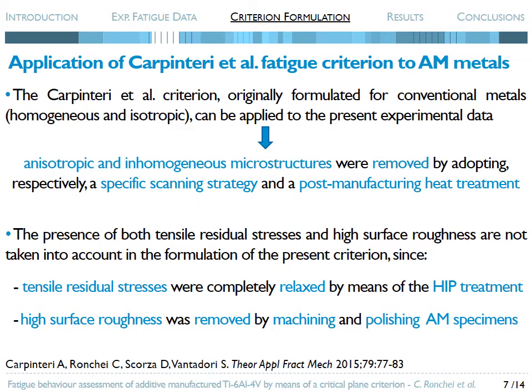The above fatigue tests are hereafter simulated through the critical plane-based fatigue criterion proposed by Carpinteri and co-workers. Before presenting the detailed formulation of such a criterion, some remarks on its application to AM metals are needed. As a matter of fact, the Carpinteri et al. criterion, originally formulated for conventional metal, that is homogeneous and isotropic, can be applied to the present experimental data, since the anisotropic and inhomogeneous microstructures of the present AM metal were removed by adopting, respectively, a specific scanning strategy and